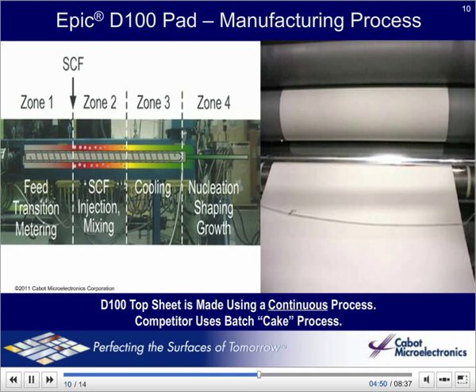CMC has 2 unique approaches to make pads. In the D100 process, we dissolve the rubber resin into carbon dioxide at high temperature and pressure, at a point where the CO2 is supercritical. Not quite a gas, but not quite a liquid either. Then we extrude the supercritical mass through rollers, and as the sheet enters the atmosphere, it cools, quenches, and depressurizes. The rubber hardens and the CO2 turns into a gas at the same time, leaving it very uniformly porous on the inside.